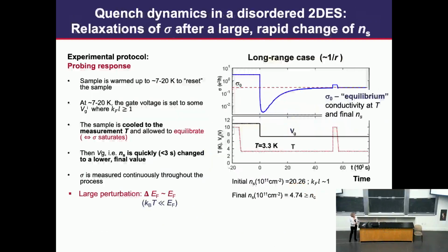The protocol is very simple. We'll start with the long-range case. Basically, we cool the system down to measurement temperature at some high density where the system is metallic, where nothing interesting happens. Then, at time equals zero, we reduce the density, the gate voltage, instantaneously.